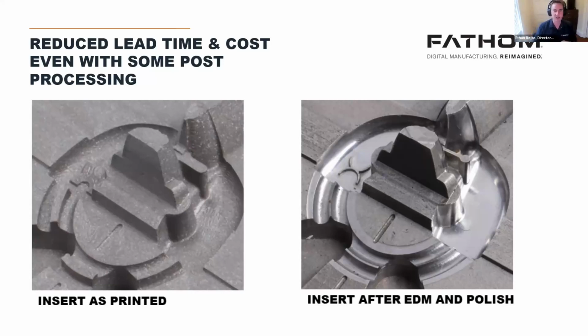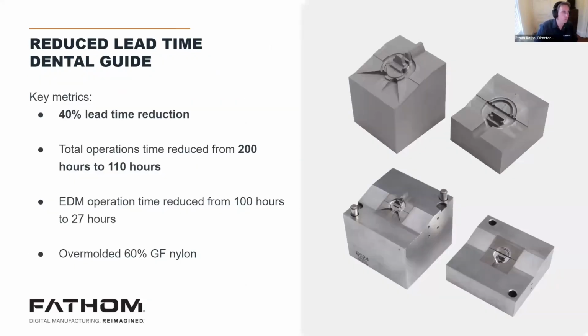So they went ahead and burned it afterwards. They printed a little bit oversized. Then they went through and polished it up afterwards. So you can see that burning process for some of these really, really thin features that are in here. But even with that, they still reduced the lead time by 40%, operation time from 200 hours down to 110. And most of that came from removing the EDM hours. 100 hours of EDM was traditionally going to be required. They moved that down to just 27 hours. And this was overmolding a 60% glass filled nylon. So really good application here as well.